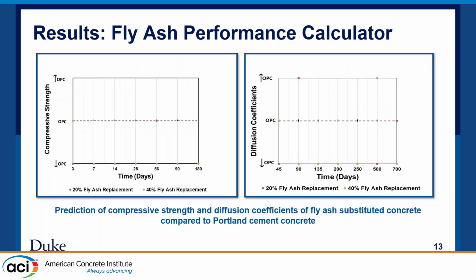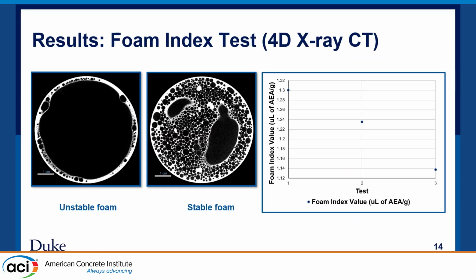If we do not get the desired result from the substituted concrete, then we can also use those fly ash or coal combustion ash as filler materials, which is well known as controlled low strength materials. And this is the result from a foam index test. To the left, there is the X-ray CT scan of the foam test we did. The first one is for the unstable foam, and the second one is for the stable foam. And to the right, there is the amount of air entrainer we have to use for the concrete.